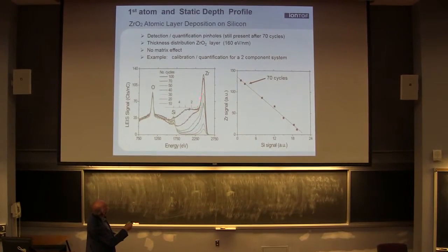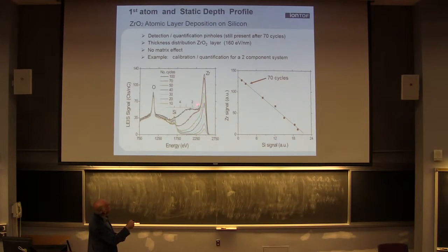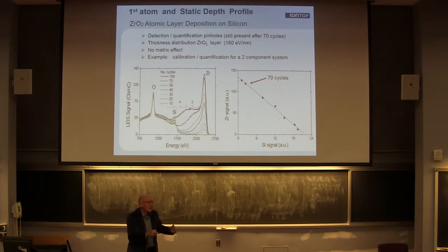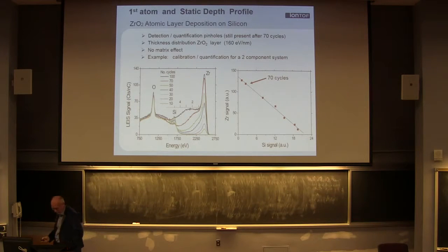On the other hand, there is not only just the peak, you see this background tail at the low energy side, and that gives you a depth profile, and here I've indicated the scale. So for instance, for the black curve after 100 cycles, you see I have more or less a complete monolayer, and there are already at the same time places where the layer is 3 nanometer thick, and at other places it is less.